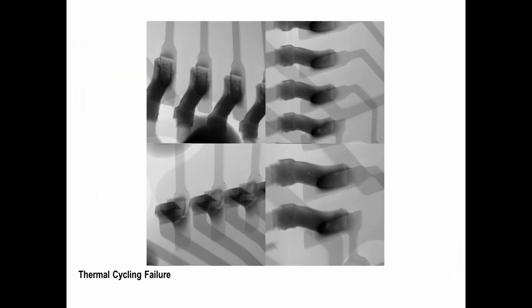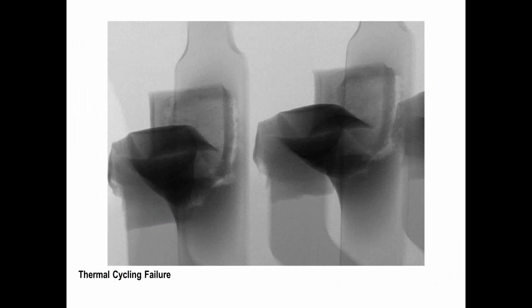And what actually happened here is somebody applied conformal coating, which is fine, but they filled up the complete area underneath the package, and during thermal cycling, the conformal coating expanded and contracted to such an extent that it actually caused the solder joints to lift. This is something that I was shown at an exhibition in the US when I was doing some X-ray work at the show.